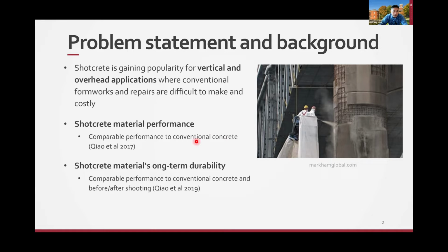And also, the previous studies have shown that in terms of long-term durability, such as freeze-thaw, there was not much difference between before and after the shooting. And as you have seen from the picture, this shotcrete was shot to the structure instead of cast like conventional concrete. So there was a concern that before or after shooting, the properties of the concrete may have been changed, but based on the previous study, we have not seen much difference.